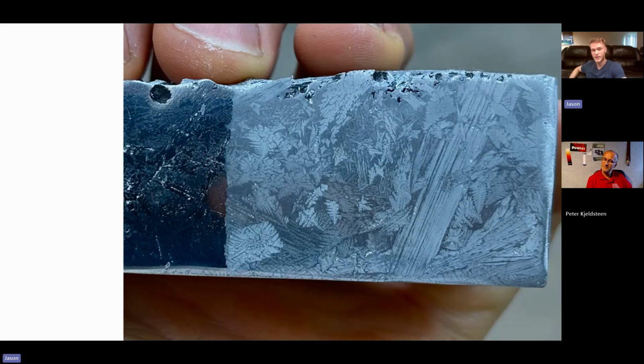And so this etch is actually anodizing. And it's anodized in a really untraditional electrolyte bath. It's actually anodized in a baking soda electrolyte. And so I just uploaded a video on why I think this works. But to sum it up, I think the eutectic region is building an oxide layer, while the intermetallic region is precipitating aluminum hydroxide. The aluminum hydroxide is very white, and so it causes the intermetallic layer to pop, while the eutectic remains more dark because it just has the oxide layer on top of it. I don't know if we'll have time to go through that whole mechanism, but I have a video if you want to check it out.